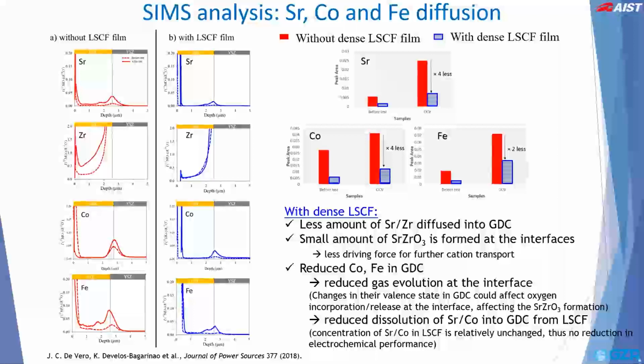Here, we removed the LSCF cathode and performed depth profile analysis across the GDC layer and YSZ electrolyte. Shown on the left are the normalized SIMS profiles for the various elements. Here we can see the evidence of extensive diffusion of strontium and zirconium across the GDC interlayer without the LSCF dense layer. In contrast, these are significantly decreased for the case of the sample with the dense LSCF layer. We also find that the extent of cobalt and iron diffusion, evidenced by the presence of a peak at the GDC-YSZ interface, are also similarly reduced. In other words, by improving the stability of the LSCF-GDC interface, we were able to consequently mitigate the strontium zirconate formation and improve the long-term stability of the cell.